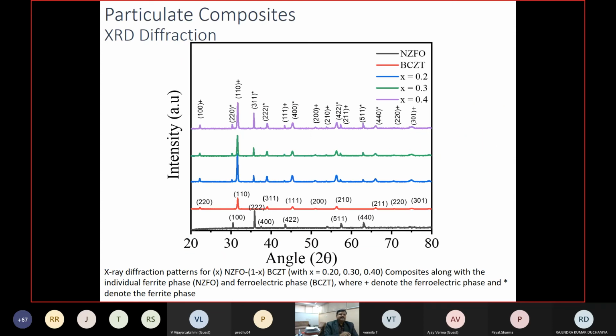Now you can see the particulate composite. Particulate composite means we are not preparing the laminates. We are just mixing the powder of ferroelectric and ferrite. Here, at the bottom of this figure, the lowest XRD pattern is for nickel zinc ferrite. It has some particular peaks. Then the red curve is for BCZT. Then the blue ones are for the composites for x equal to 0.2, 0.3 and 0.4. Here you can see separate peaks for ferrite and ferroelectric material, right? That means it is a composite. If you were not able to get the characteristic peaks of ferrite and ferroelectric, it would mean they have formed some new structure in the material. Here it is clearly seen that they have not generated any new structure, they are just composites.